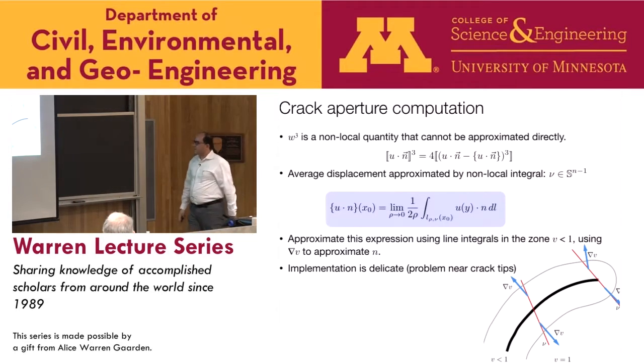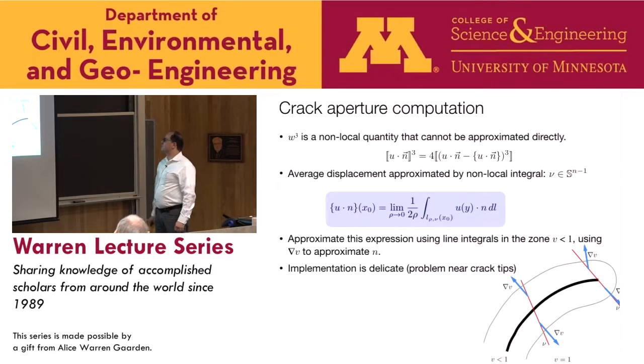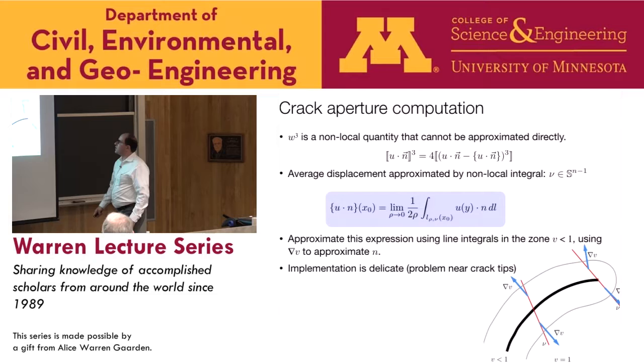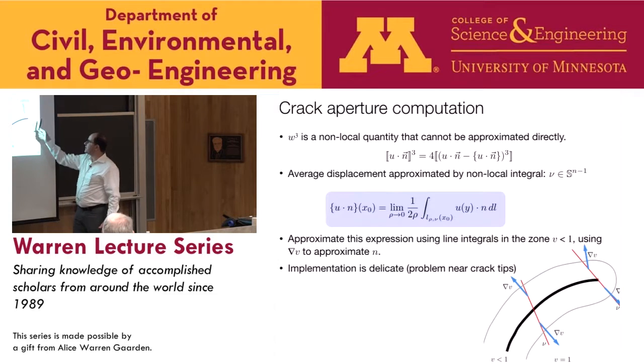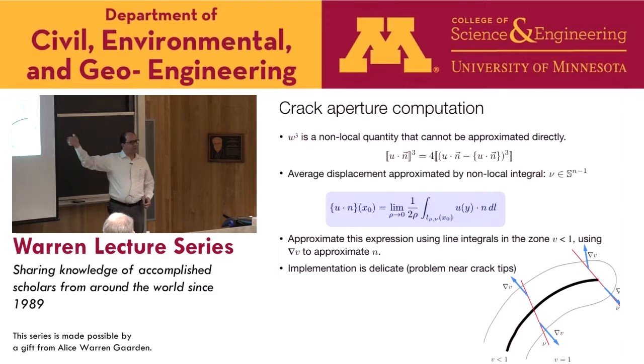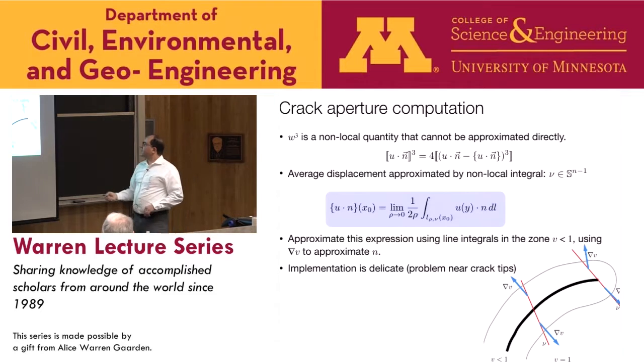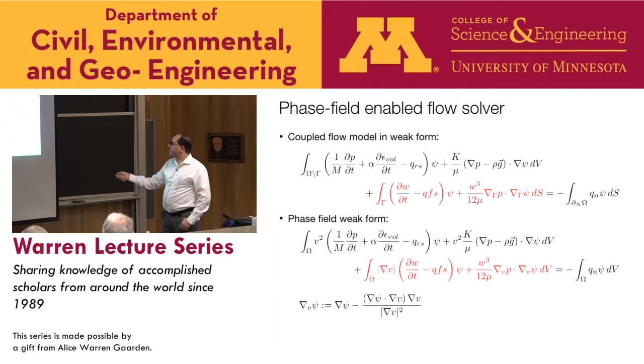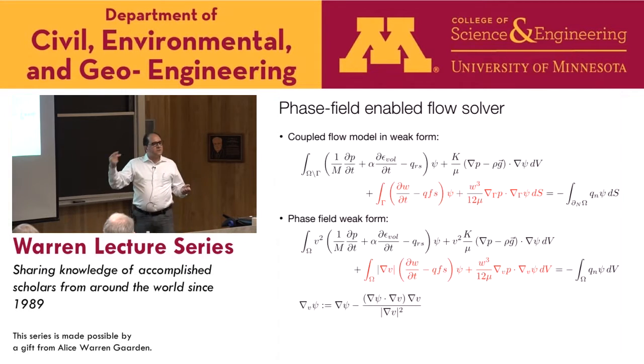And so we spent quite a while trying to compute these, to identify this problem. And in the end, what we do is simply look at the spatial variation of the gradient along the line. If the average gradient is far from 0, it means that our line is near a crack tip, so you can discard the information there. Okay. And so now we know how to compute our crack average displacement. If you know how to compute the average displacement, we can compute the aperture, or the cubic aperture. So we know how to completely formulate the coupled flow problem in a reservoir and in the fracture without an explicit representation of the fracture, but just using the phase field representation of the fracture.